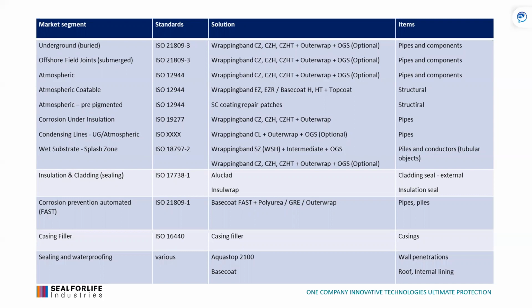Corrosion under insulation has its own set of standards. Wet substrate, splash zone, again, another set of standards, because you have to apply it on a wet surface. You have to apply it with a high chloride content in salty areas and salty environments, and yet withstand lifetime, but also impact resistance from whatever floats in the sea, trees, branches, but also boats that impact the piles, and so on. Insulation and cladding, which is part of the sealing, so you can actually seal off the cladding for extra lifetime to eliminate the water ever getting into insulation.